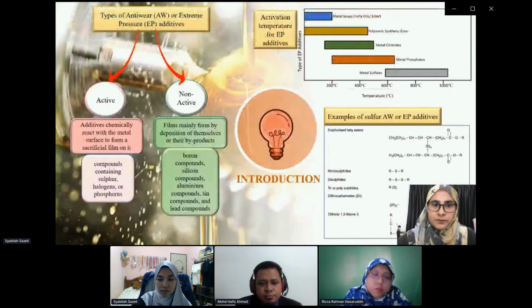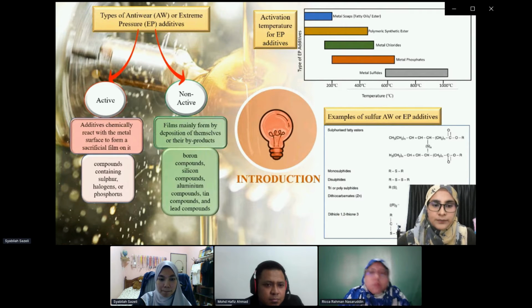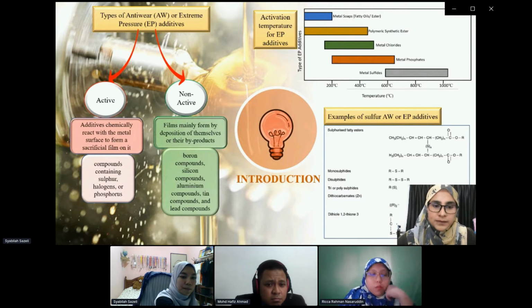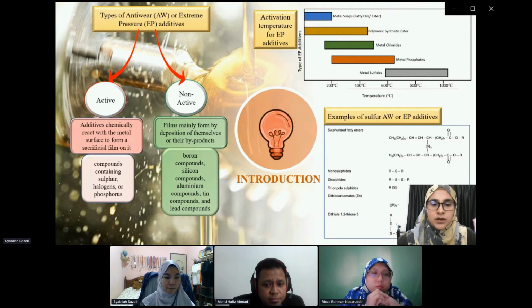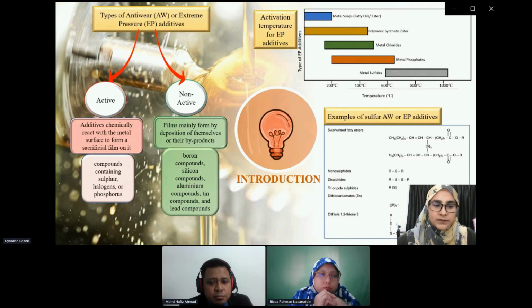For types of additives, there are active and non-active additives. The active additives chemically react with the metal surface to form a sacrificial film on it. For non-active, the films mainly form by deposition of themselves or their byproducts. Examples of active additives are compounds containing sulfur, halogens or phosphorus, while non-active are boron compounds, silicon compounds, aluminum compounds, tin compounds, and lead compounds.